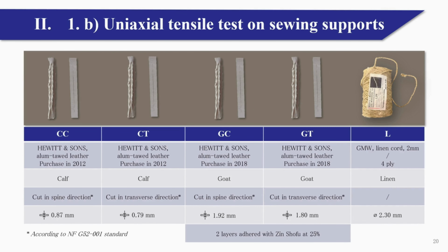A tensile test was also performed to characterize the mechanical behavior of sewing supports. The sewing supports selected for samples are the most commonly observed in medieval manuscripts: split, twisted, and flat thongs made from alum-tawed skins of calf and goat, and linen cords. As the skin is anisotropic, the thongs were cut in both spine and transverse direction, according to the NF G52-001 standard. Due to its thinness, the goat skin was lined with a second layer, which was adhered using wet starch paste.